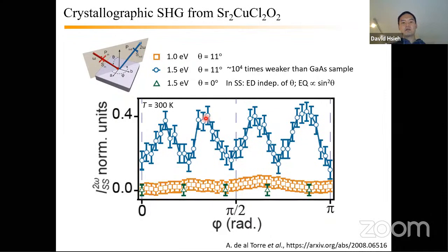And if you go just a little bit off resonance, if we come in with, for example, 1 eV under the same experimental geometry, we don't see anything. So that's why we think we're riding on this resonance. And moreover, this is taken at 300 Kelvin, above T_N. You can distinguish what type of process you're looking at. Are you looking at an electric dipole process from the surface or an electric quadrupole process from the bulk? And at least in this SS channel, which we like to use, we know that the electric dipole process has to be independent of the angle of incidence theta.